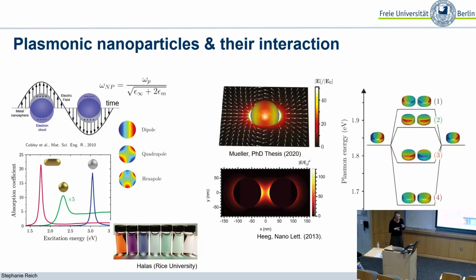You can describe this with the same concepts of hybridization that you use for the formation of diatomic molecules, but with the optical excitation this time instead of the electrons. I have a nanoparticle with a little dipole, indicated here with blue and red, and a second nanoparticle. If I bring them close together, their dipoles interact. I can line them parallel along the axis, anti-parallel along the axis, parallel perpendicular to the axis, or anti-parallel perpendicular to the axis. Because of the interaction of the optical near fields, all of them will have slightly different excitation energies.